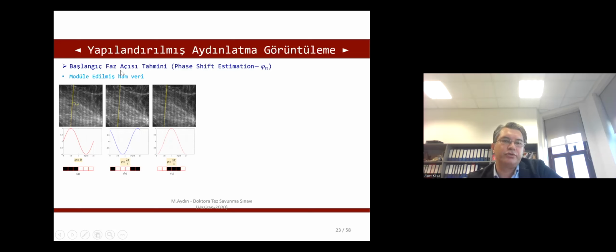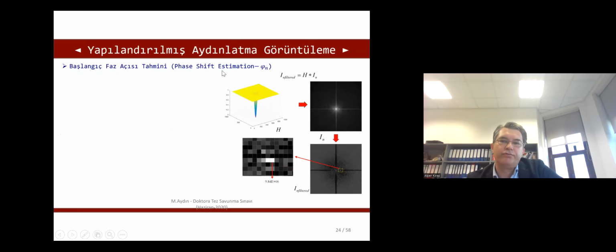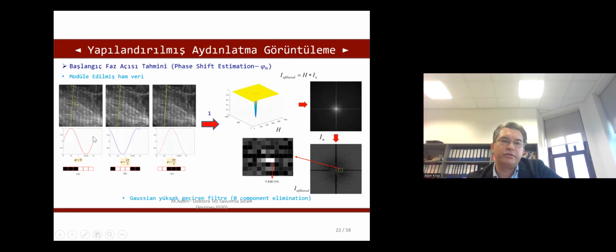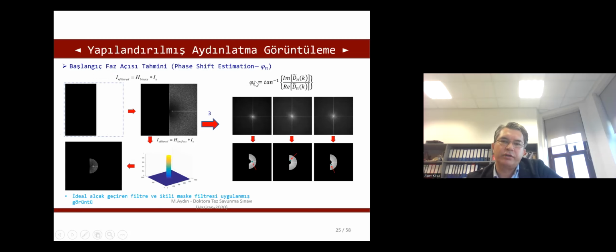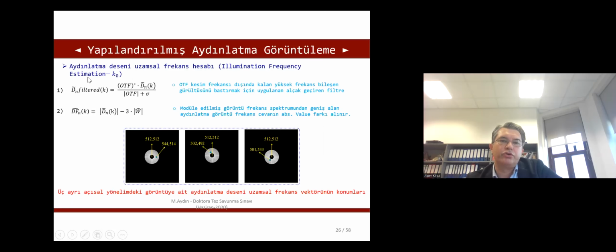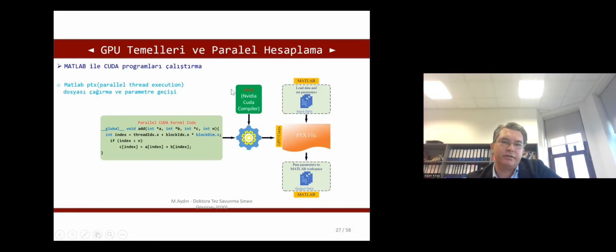In this algorithm, you need to do a phase shift estimation of your fluorescence signal. For that, you go to the frequency domain of the recorded images, and in the frequency domain, you calculate the phase by looking at these shifted spots. You have to first determine the locations of the shifted spots, then find the peaks of these shifted spots, and at the peak locations you calculate the phase, and you also calculate the illumination frequency. You estimate the illumination frequency again by locating these shifted peaks in the spatial frequency domain. We have implemented this in a GPU-based algorithm. The PhD student Musa Aydın wrote this in CUDA programming with NVIDIA GPU chips.